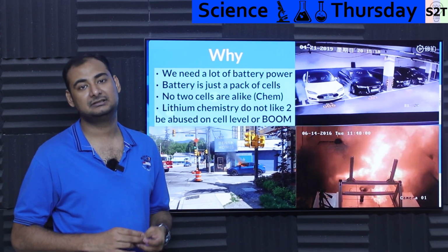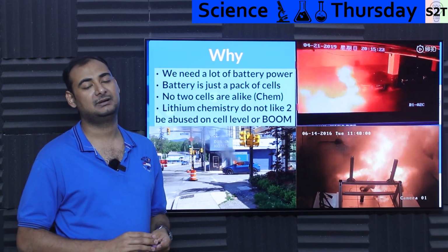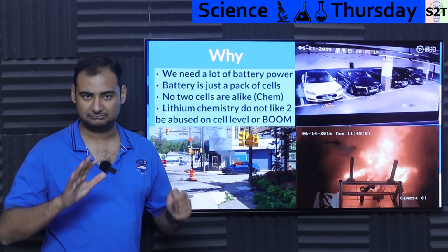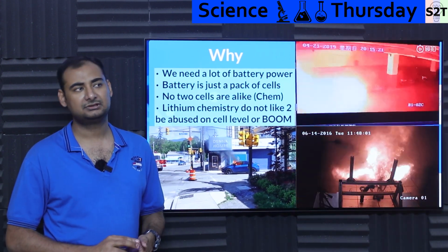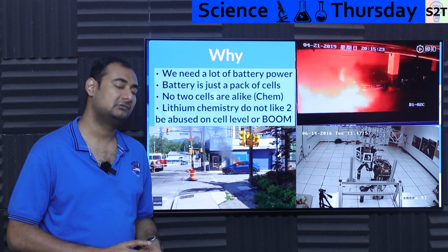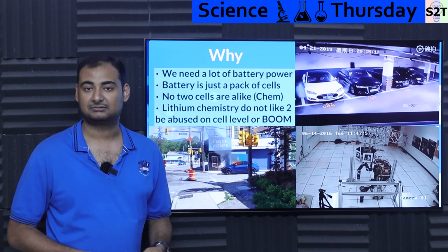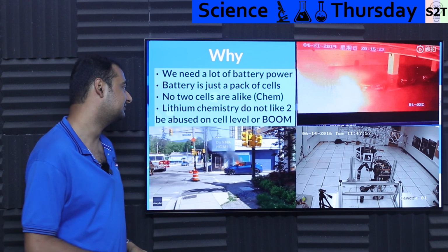If you have a low grade manufacturer, one cell to another could be off by 10%. If you have a good branded cell, but low cost, it could be about 5% off. With a very high quality one, you are looking at 1 to 2% off, but it will always be off. Sometimes you may luck out and get a bit more capacity, sometimes you will not. It's a law of physics. Do not fight it. It's real. That's what it is.